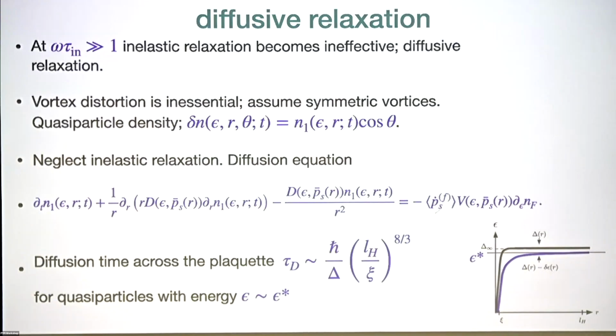Okay, so now as you increase the frequency, the inelastic contribution decays as 1 over omega squared. Eventually, the inelastic relaxation becomes ineffective, and then the diffusive contribution takes over. Then to discuss this contribution, let's forget inelastic relaxation and discuss just the diffusion equation. Also, importantly, now the distortion of the vortex is not important. You have a dipole and a distortion of the density due to the electric field. It diffuses, and the characteristic time scale in this case is tau d, the diffusion time of quasi-particles across the vortex at these energies near the percolation threshold. And it scales with the vortex distance as this weird power of 8/3 with the intervortex distance.